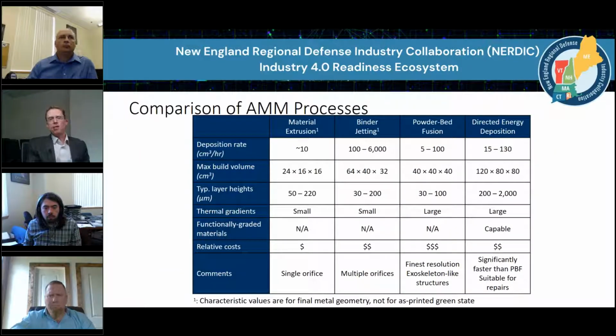If we look at a comparison of these processes, the things I want to draw your mind to are right here. We have the thermal gradients. Material extrusion and binder jetting typically have very small thermal gradients, so you end up with fewer texture problems: less columnar grains, more equiaxed grains. With powderbed fusion and directed energy deposition, it's very possible to end up with grain textures that are less desirable. The other thing I'll call your attention to is the relative cost.